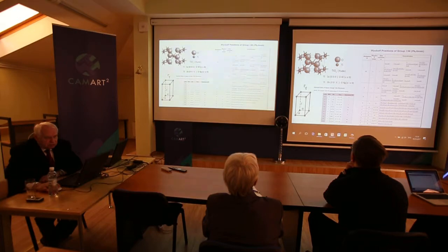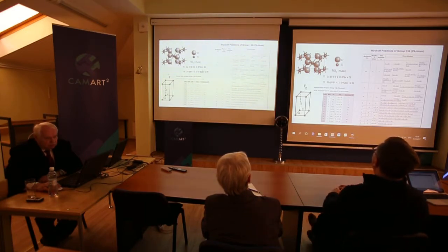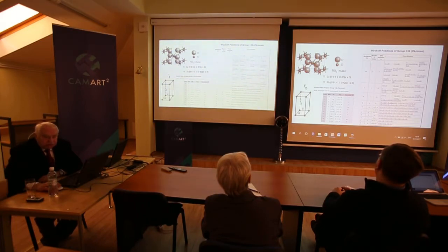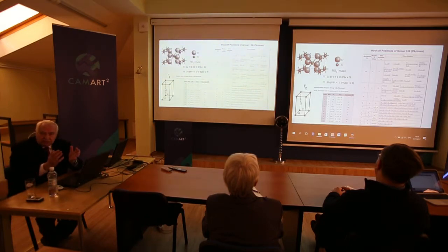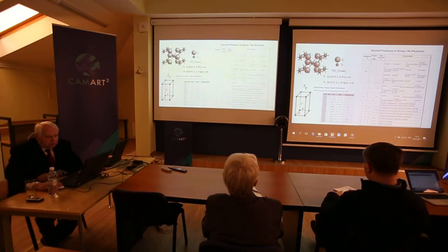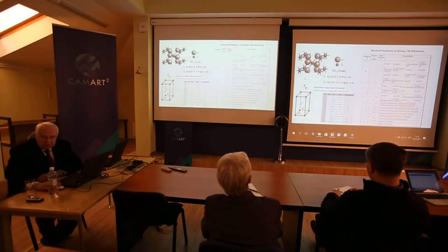So let's look at this rutile structure. This is titanium in the center of this tetragonal, primitive unit cell with 2 formula units. So we need to find 2 titaniums and 4 oxygens. 1 titanium belongs to the whole unit cell. This is 1. And what about these ones? Dima, what do you think? How many of these belong to this unit cell? Atoms or parameters? Atoms. Atoms. I remember 4.